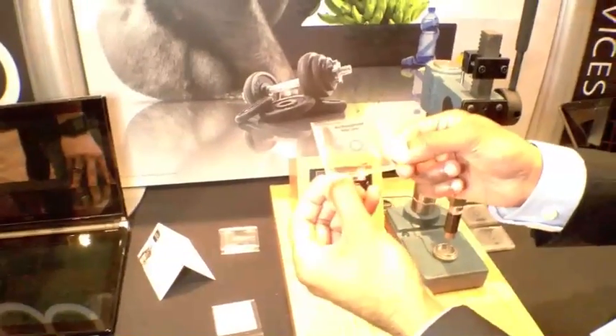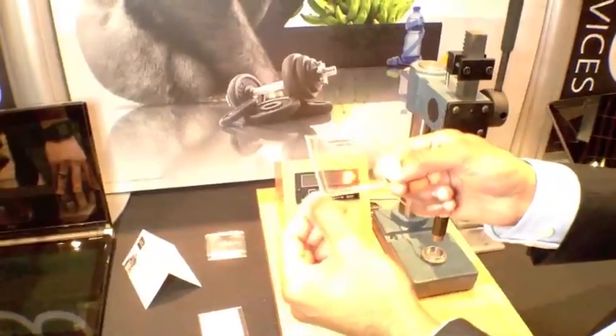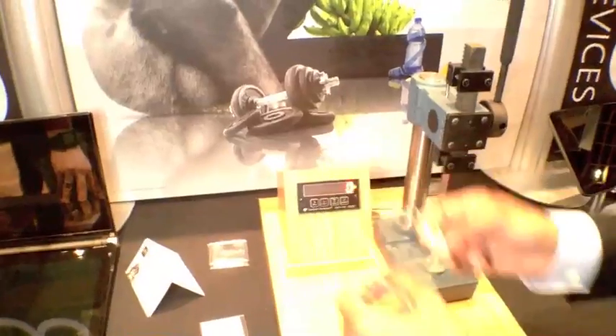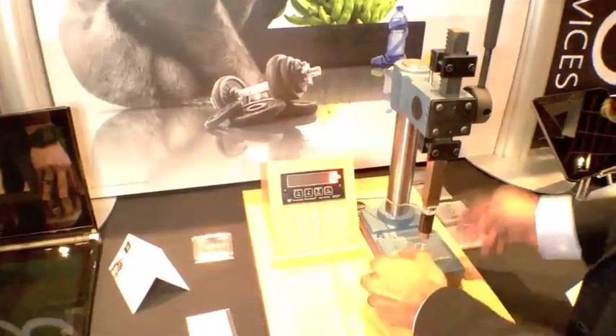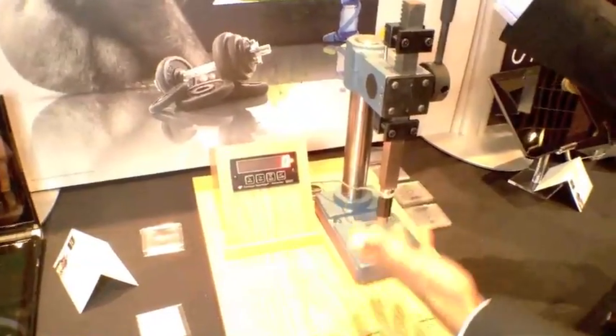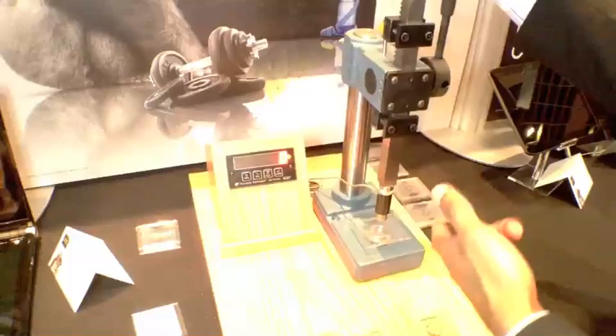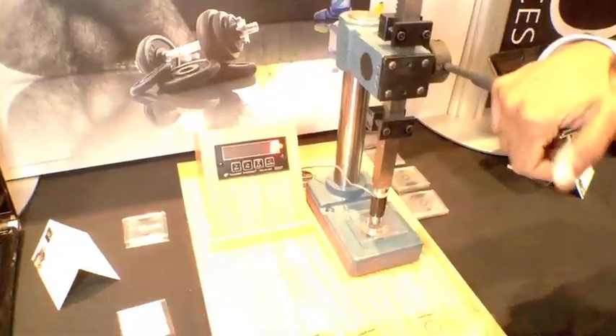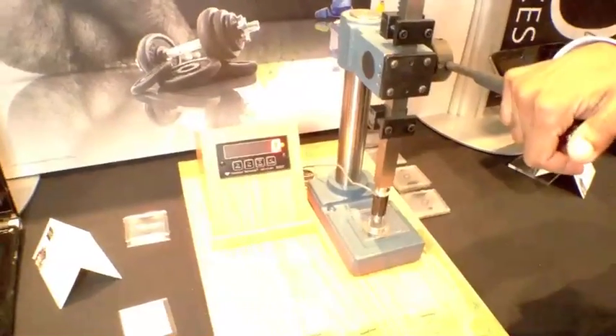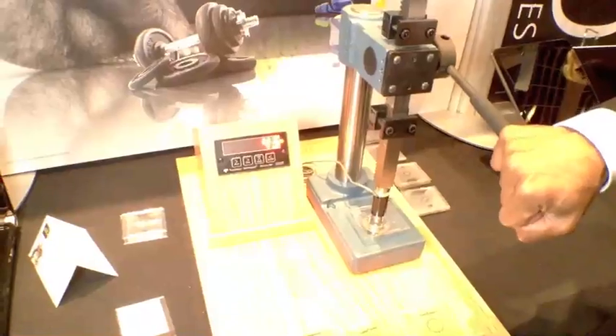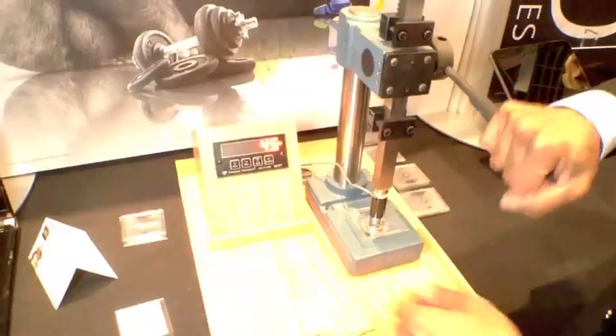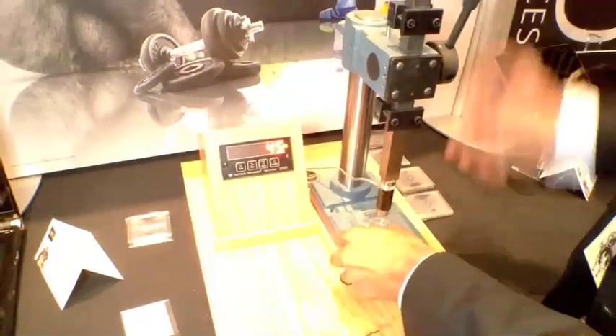I'll start with non-strengthened soda lime glass. This is a 1.1 millimeter plate. Put it in this press. I push down and see at what force the glass breaks. The glass is weakened because of the abrasions. 45 pounds. Non-strengthened soda lime.